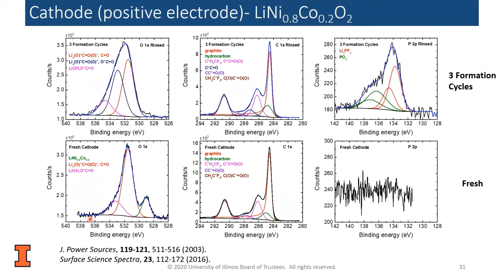So let's look at some of the XPS from these new batteries. And so on the bottom here is a fresh battery. And so this is the battery just upon assembly, where you take a slurry of the oxide, the binder, and the carbon black, and basically paint it onto the electrode and on the current collector and let it dry. And so the battery is not going to behave very well initially after assembly. So what is done is what are known as formation cycles. And then this is how you clean off maybe the surface oxide that's on the particles during initial formation, and then form the SEI layer.